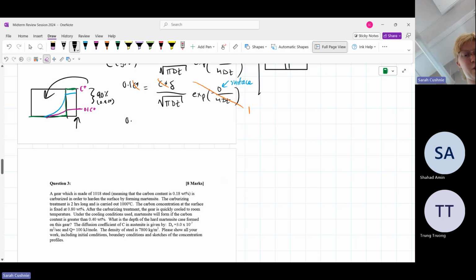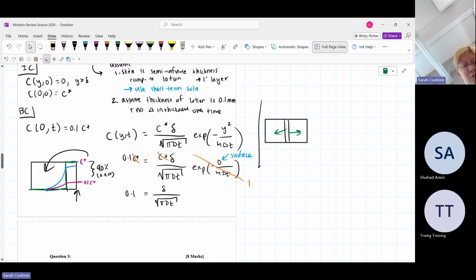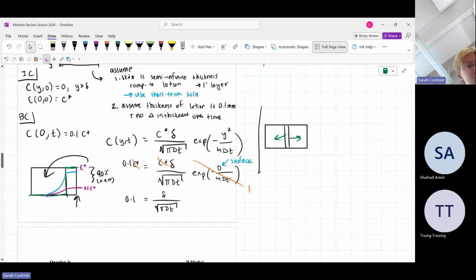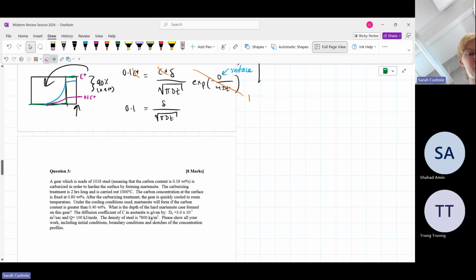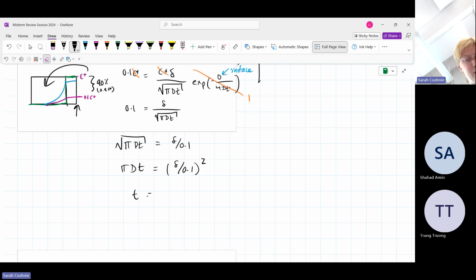So now we're left with 0.1 is equal to delta over root pi Dt, where delta is the initial thickness of that layer, which we assume to be 0.1 millimeters. So now all you have to do is solve for t. So the root of pi Dt is equal to delta divided by 0.1, or pi Dt is equal to delta over 0.1, squared. t is equal to delta over 0.1, all squared, times 1 over pi D.